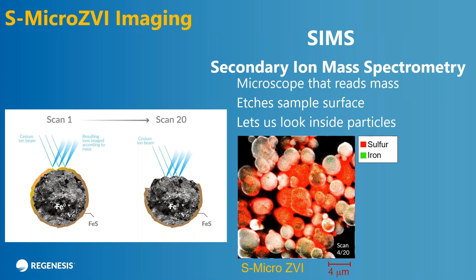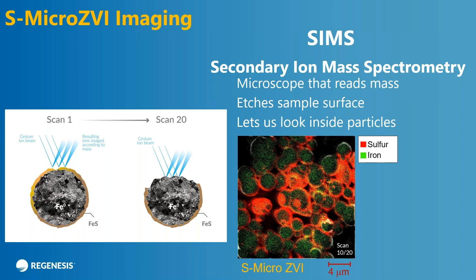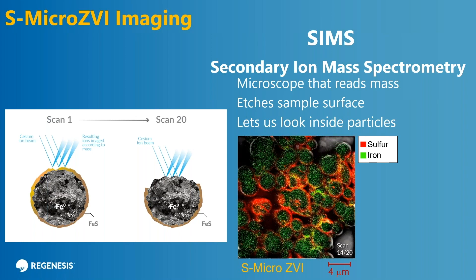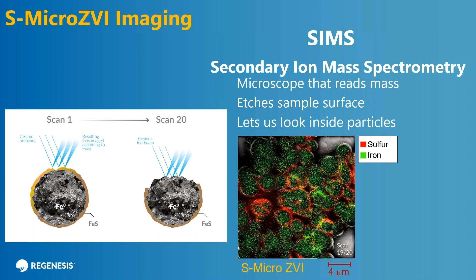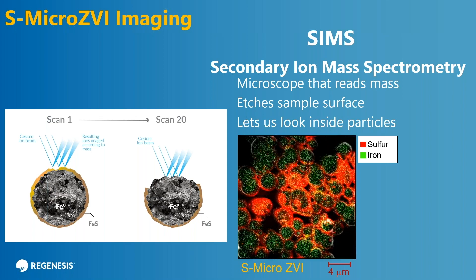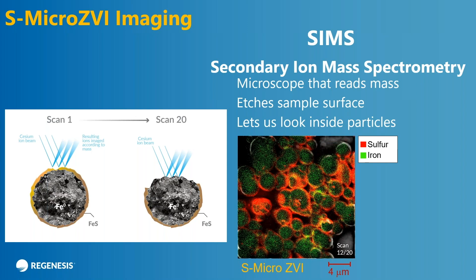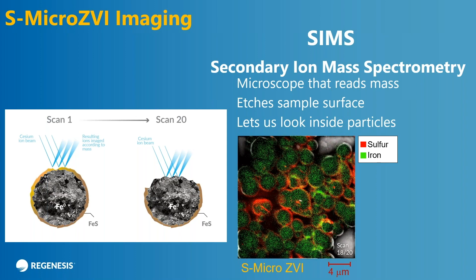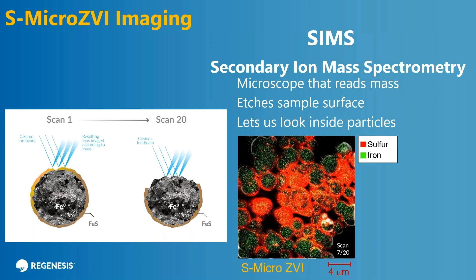Here's a slideshow. At the beginning it's all red — you see that indicates that you have a fully sulfidated surface. With time, as we go further in, all you see is green with a little bit of a red halo around the outside of the particles, which depicts the sulfidated layer at the periphery. So this really confirms what we know about the particles — that we actually have a very good core shell microstructure.